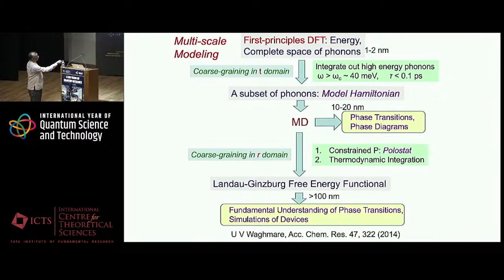You start from DFT calculations, which give you access to processes on the scale of a few nanometers. We do coarse-graining in the time domain by integrating out the high energy degrees of freedom, in this case phonons, and get a model Hamiltonian, which is focused on unstable modes, and that can be used in molecular dynamics or Monte Carlo to predict material specific aspects of phase transitions, not necessarily the universal aspects. Of course, universal aspects are also available to us, but our focus is on material specific aspects.